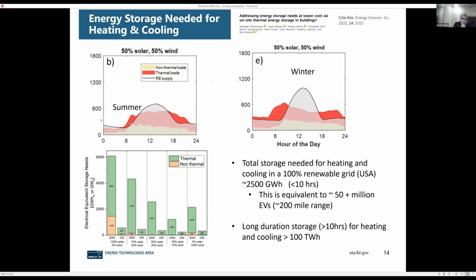So what we found out, as you can see, first of all, the black line is the supply curve. So that is the supply of electricity. No wonder it peaks at around noon, because this is 50% solar, 50% wind. The gold is the non-thermal load in the building, right? And the red is the thermal load. And you can see in the shoulder hours here, you don't have any electricity available, but you have demand. That's where storage becomes very important, because you have extra electricity available here.